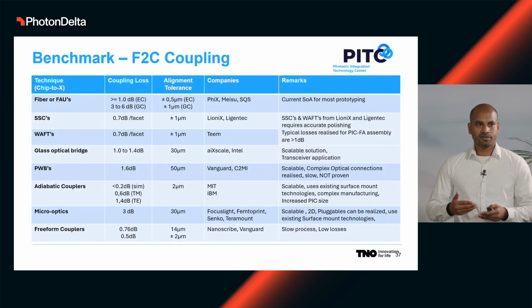We benchmarked various fiber-to-chip coupling techniques, and we see that the current state of the art for most prototyping is connecting it with the fiber. We see losses of about 1 dB with a 0.5 micrometer alignment tolerance for an edge coupling, and 3 to 6 dB with an alignment tolerance of plus or minus 1 micrometer for a grating coupler. Some of the companies that provide these services are PhiX, Meisu, and SQS.